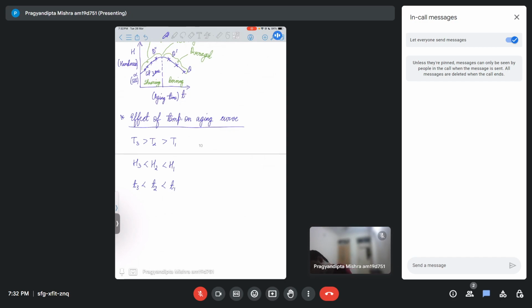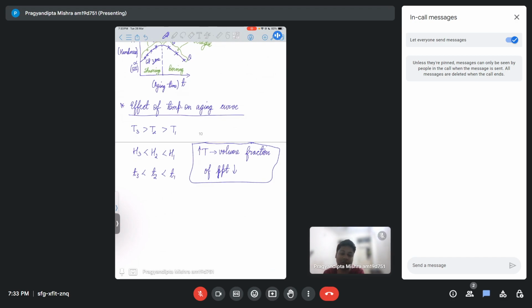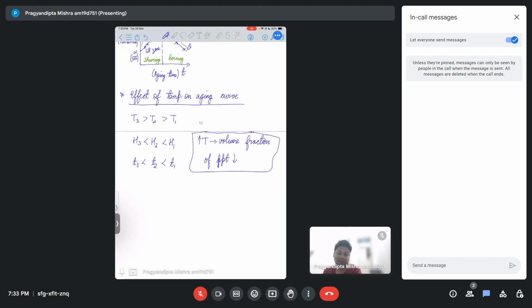Now, why is this happening? Because with an increase in temperature, the volume fraction of the precipitate would reduce. Volume fraction of precipitate goes down. Okay. Now, since volume fraction goes down, hardness will also go down, and also the time taken to reach peak hardness will also go down. So therefore, you will see this kind of relationship between temperature and aging curve. Okay. So this is another relationship that you can keep in mind.